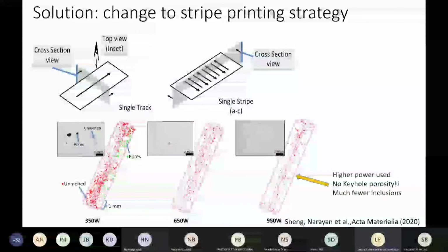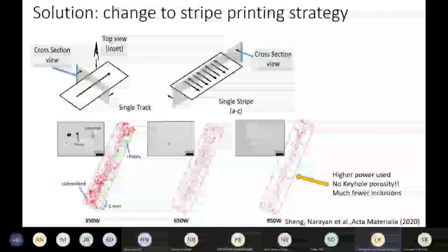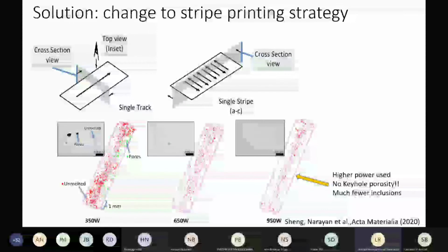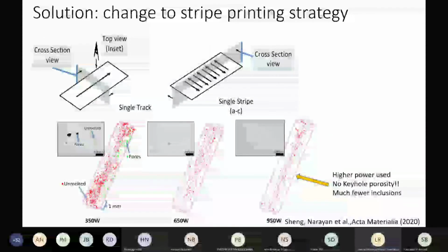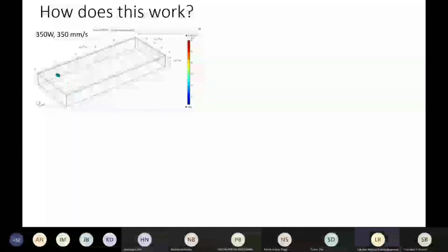In fact, for very high power, when we used them, we did not observe any keyhole porosity and had much fewer inclusions. So this printing strategy itself was able to give us a very high quality material. In fact, it eliminated keyhole porosity completely, which is actually a very significant landmark. And how does this work?